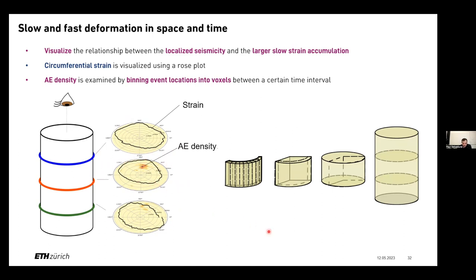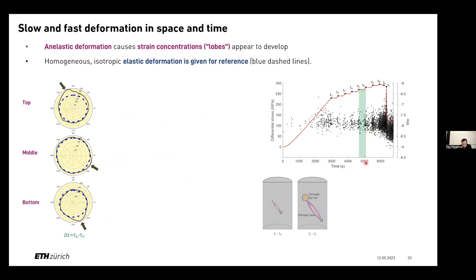So if you keep this in mind, if we start at this part of the experiment, what we see is that even before there's a lot of seismicity, so right now there's very little seismicity in this sector, we see anelastic deformation occurring. Meaning if we looked at the rose plot, it would be essentially a perfect circle if it was isotropic, homogeneous deformation of the sample. We already see, without even localizing of seismicity, the development of these lobes, and the lobes could be considered potential strain concentrations that are developing from preferential movement.